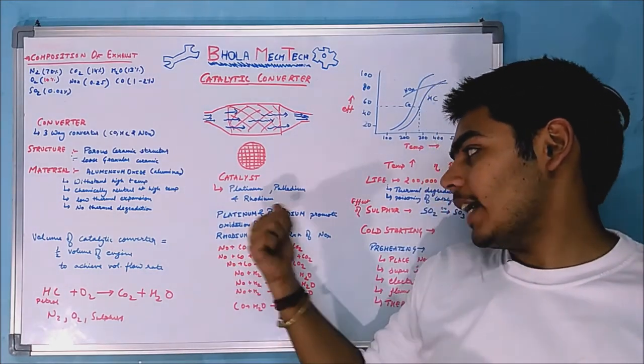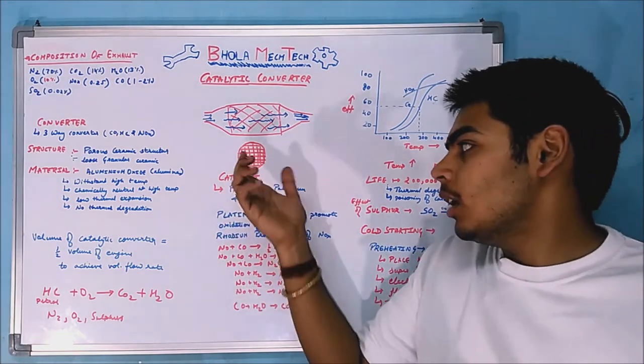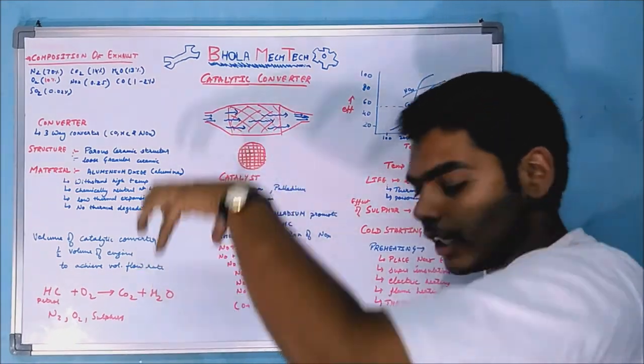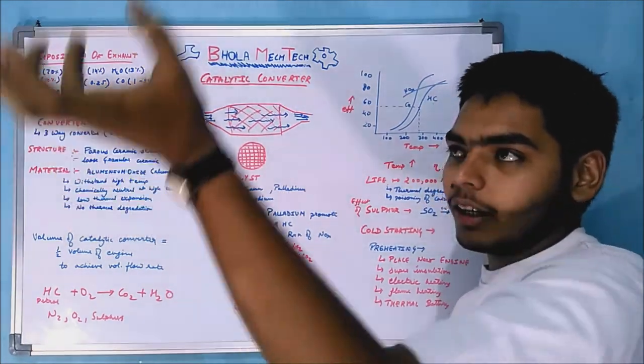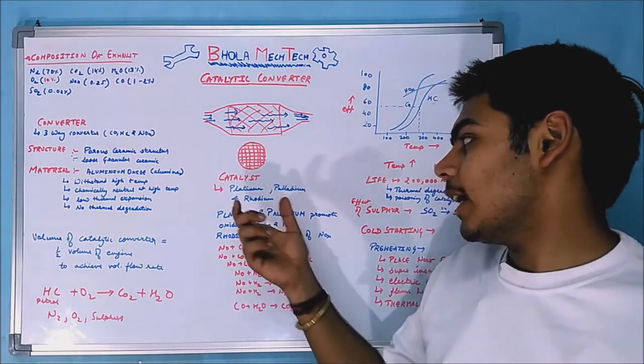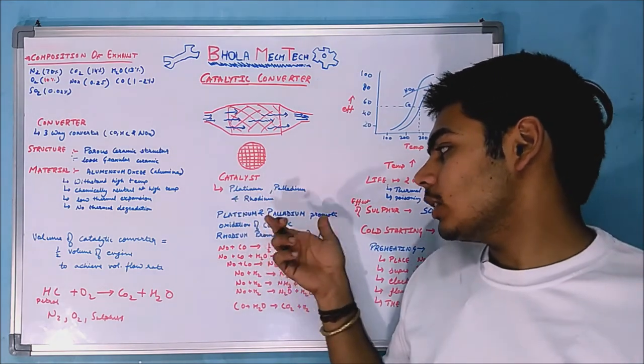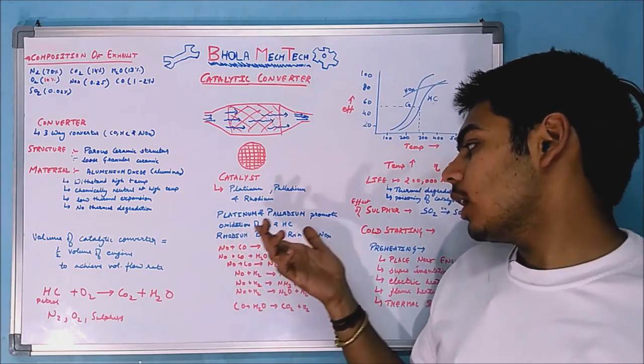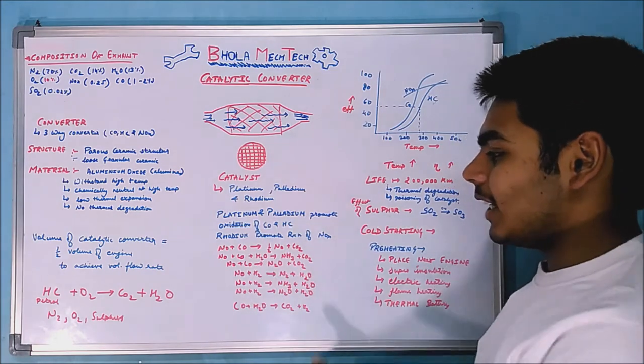For the treatment of these gases, we use catalysts. These catalysts are platinum, palladium, and rhodium, which are applied on the walls of the pores — the catalytic converter is dipped in the chemicals, taken out, and then subjected to heat treatment before use. Platinum and palladium are used for the oxidation of carbon monoxide and hydrocarbons, while rhodium is used for the reaction of NOx gases.